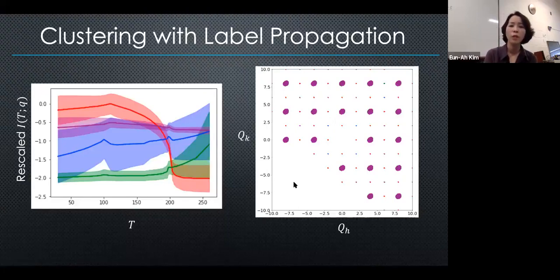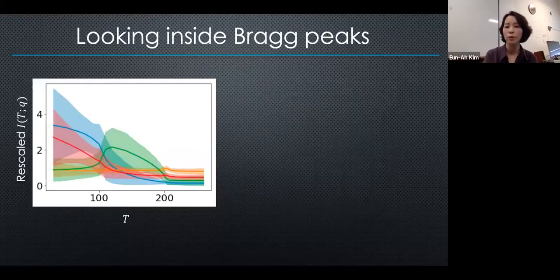However, we are seeing very little about the lower transition, although there's a clear thermodynamic signature. So when we wanted to look inside the lower transition, what we did was open up each Bragg peak, because the lower transition, if the conjectures are correct, would be an intra-unit cell transition. The only thing that can change for an intra-unit cell transition is a structure within the Bragg peak. So when we opened up the Bragg peak and redid the clustering, we found this result.